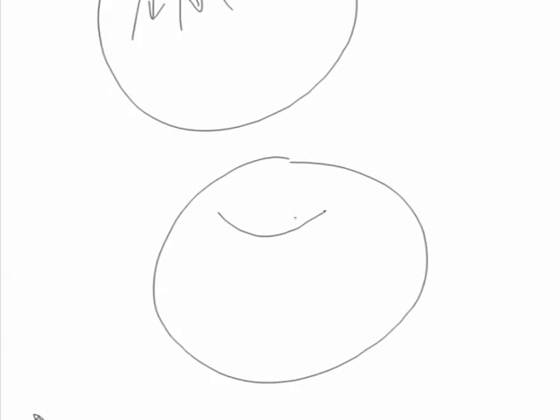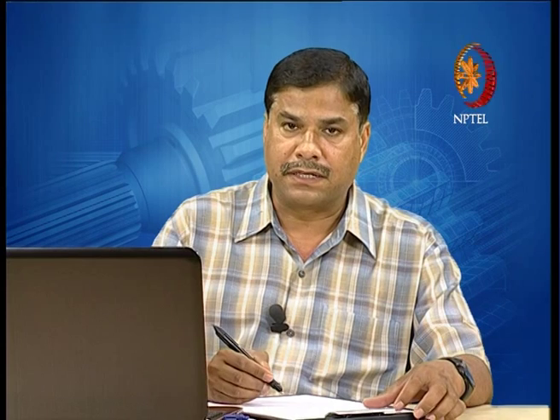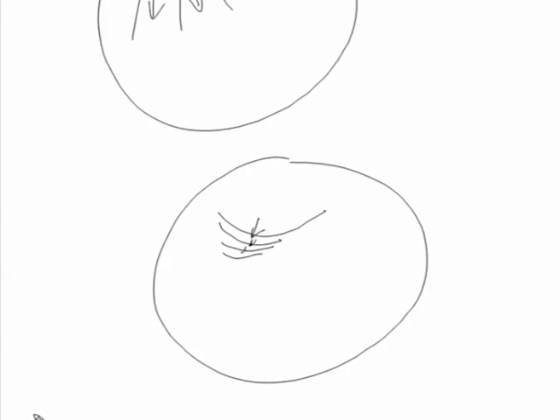And then typical striation marks on the fracture surface like this are also observed. If this is, say, a component which has failed by fatigue, then we will be able to see, step by step at the microscopic level, concentric circles being developed, indicating the presence of striations. This is the typical feature of fatigue fracture. The striations on the fracture surface at high magnification, more than 1000x or so, will be observed in a component fracture surface which has been subjected to fatigue. So the dimple fracture indicates ductile fracture, the presence of cleavage facets and intergranular fracture indicates brittle fracture, and the striations indicate fatigue fracture.